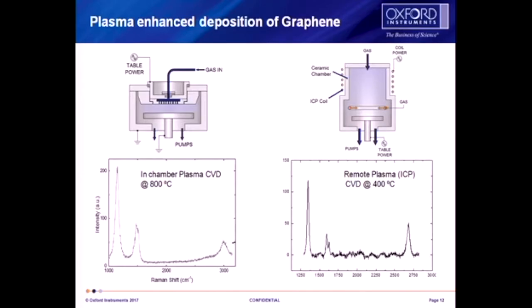And we have recently started looking at actually doing it by remote plasma. We think this might be due to the actual ion damage from using the PECVD tool. We're looking at it in remote plasma, and that's work that's ongoing with, I think it's Gunn, isn't it, Mike? Gunn, yes. So we've got a system out in a company in a university out in Europe, and we're starting to look at that. And you can see the D peak is smaller, again increasing the quality of the material. And again, this is getting close to where you could actually use it almost in a CMOS type device.